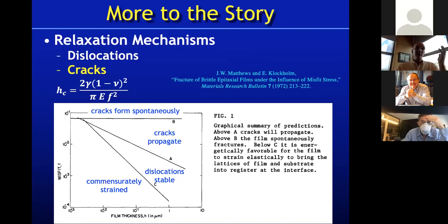It could be that you have a really strong nucleation barrier. Maybe you're growing at a really low temperature, or maybe you have a system where it's very hard for dislocations to nucleate and to move. So there becomes another regime that becomes important, and that's where films can crack. And for those of you that do synthesis, maybe you've seen cracks in your films. That means that you're doing a great job at keeping the dislocations at bay. But if there are pre-existing cracks in your films, once you get above line A here, it's then favorable for those cracks to propagate.